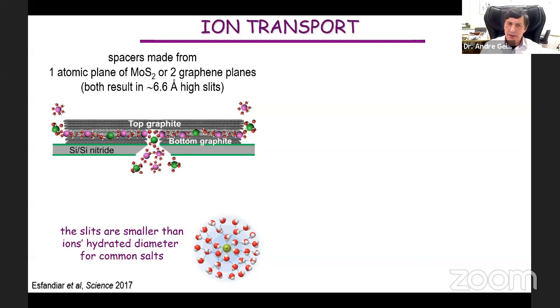And why this channel? Why not bigger channels? For a simple reason, because ions usually travel covered with a coat of water molecules, the hydration shell. It's about 3 water molecules, and this is about, for the smallest salt, 7 angstrom. So we are in the regime where the effective size of ions is comparable with the size of our capillaries. And we studied this regime. Let me go reasonably quickly through this subject.